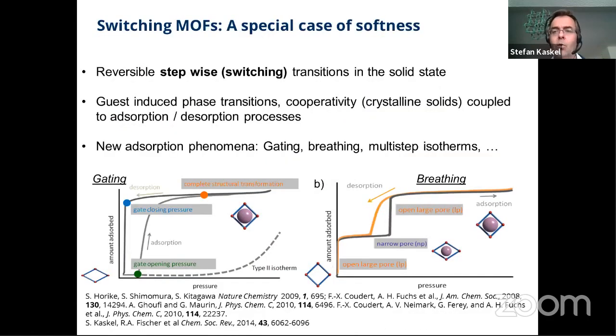So what is so special and why do I call this switchability? I think there's quite a difference as compared to, let's say, polymers that also swell when you expose them to solvents, like PMMA or whatever, because here we have a cooperative switching mechanism. The metal organic framework has a crystal structure and it changes all unit cells in parallel. And this causes a stepwise switching from a closed pore phase, for example in the case of the gate opening behavior, to an open pore phase. And this is the most simple mechanism to go from a closed pore to an open pore phase.